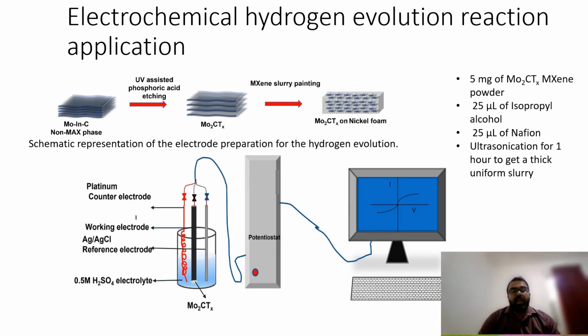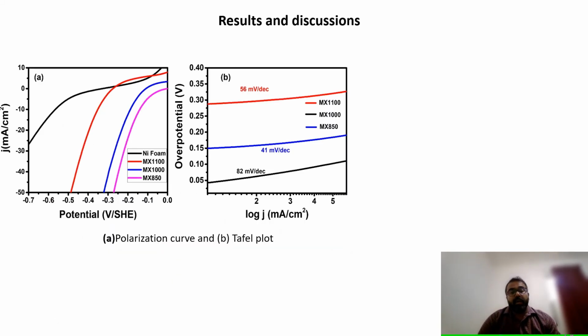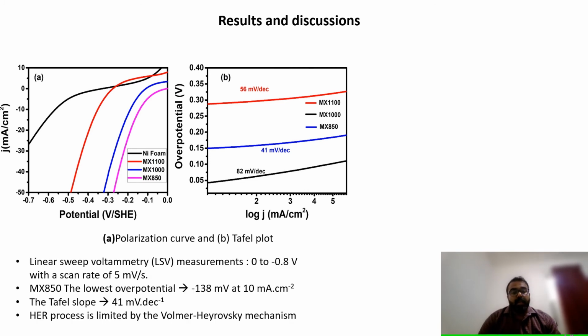For that, we used a 3-electrode system with platinum as the counter electrode, the prepared nickel foam based MXene sample, or MXene on the nickel foam, as the working electrode, and Ag/AgCl as the reference electrode in a 0.5 molar H2SO4 electrolyte, which is acidic. And we have analyzed the performance of the fabricated electrode by plotting a polarization curve from the linear sweep voltammetry, which was done in the range 0 to minus 0.8 volts with a scan rate of 5 millivolt per second.